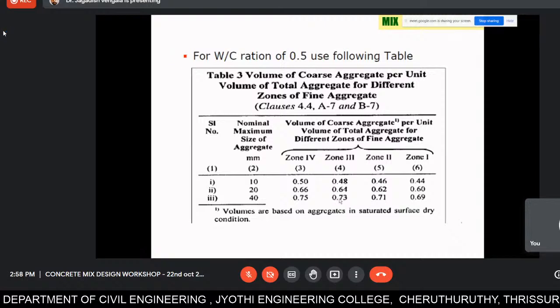Now we have to find the coarse and fine aggregate quantities. There is one more table between the water cement ratio and the volume of coarse aggregate. It is very easy to remember. If it is zone 1 with 20 mm aggregates, it is 0.6, and when the zone increases, zone 2, zone 3, zone 4, your 0.6 will become 0.62, 0.64, 0.66 with a 0.02 variation. Similarly, for 10 mm down, 0.44 it starts and it increases to 0.46, 0.48, 0.50.